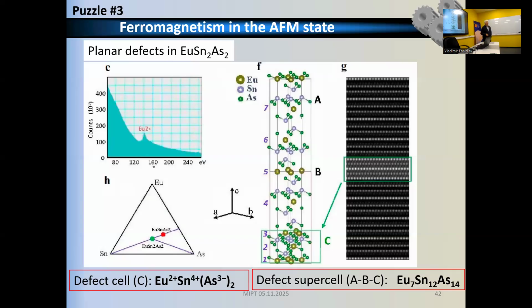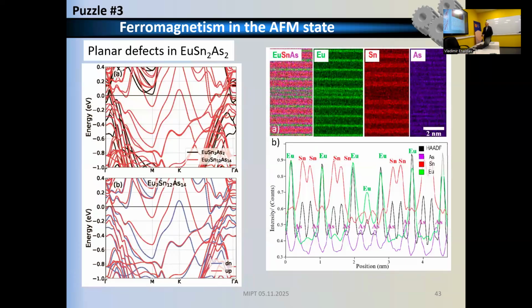What is important? That the number of europium atoms is odd. Since it's odd, it must be ferromagnetic. It cannot be antiferromagnetic. So we immediately, on this chemical analysis, already obtained that the origin of the ferromagnetism comes from defect. And this is confirmed by DFT calculations.